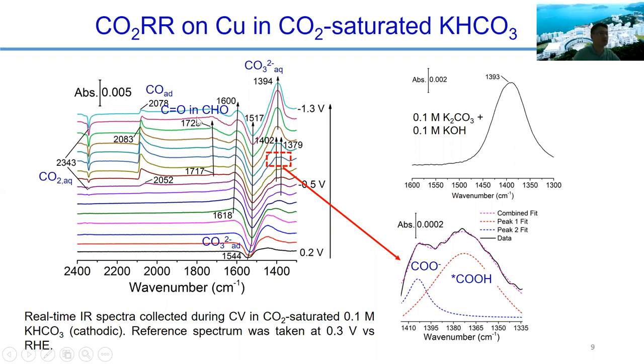This band is associated with the carbon-oxygen double bond in CHO, which is actually a reaction intermediate in generating carbon monoxide. And another band about 1600 is about the water solvated on the surface. There's also a very weak band around 1400. If you decompose it, one band is around 1400 and the other is about 1370, so this has two bands.